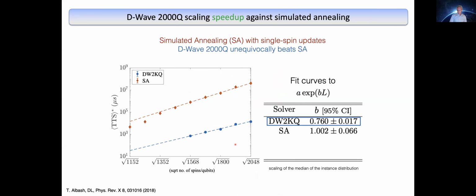So that was great. And we then use this certificate of optimality now to try to establish an actual speedup for D-Wave. And we found that there was a speedup against simulated annealing for these problems, these frustrated loops with the tunneling gadget. And that is seen clearly here. This is time to solution versus problem size. Now with optimized anneal times for D-Wave, which is the blue data, the D-Wave 2000Q now. And here is simulated annealing, and here are the slopes. And so the D-Wave slope, with 95% confidence intervals, is definitely better than the simulated annealing slope. So that was a cause for some celebration.